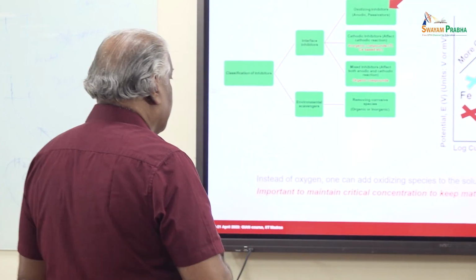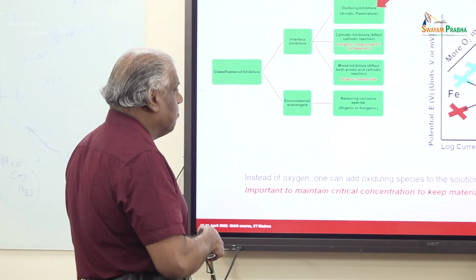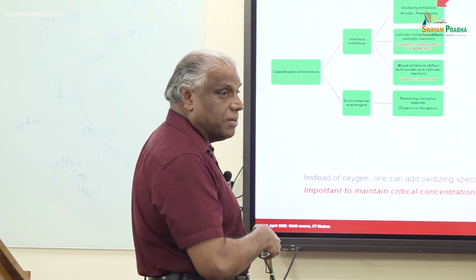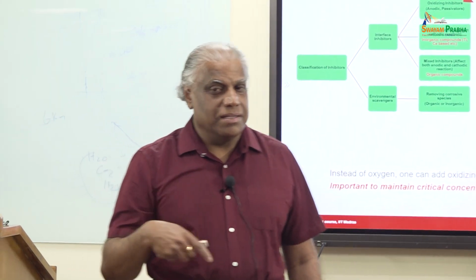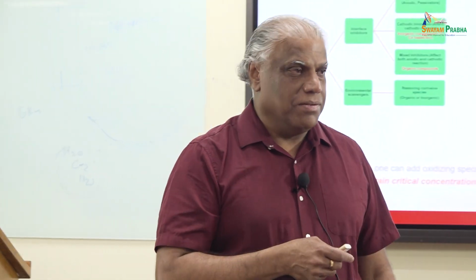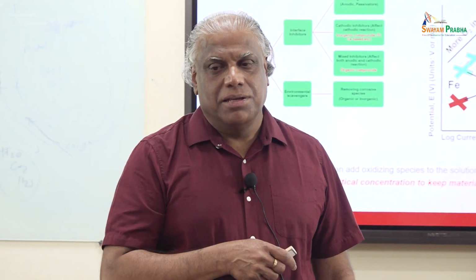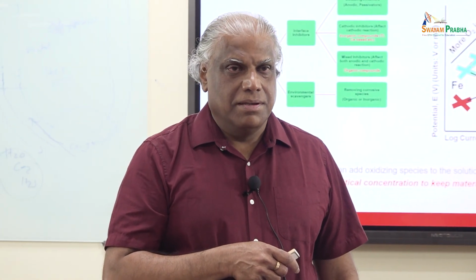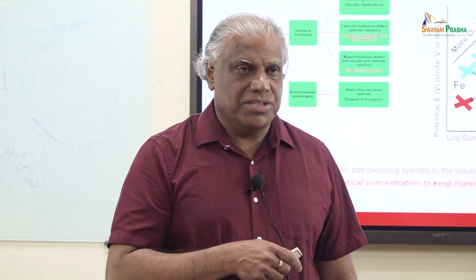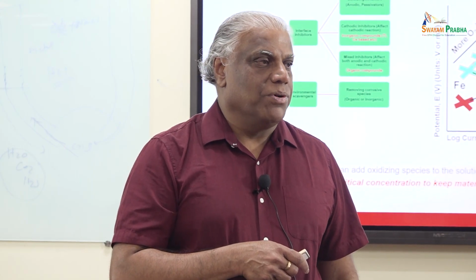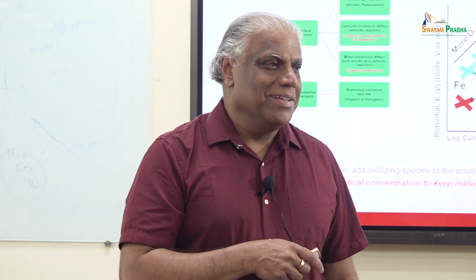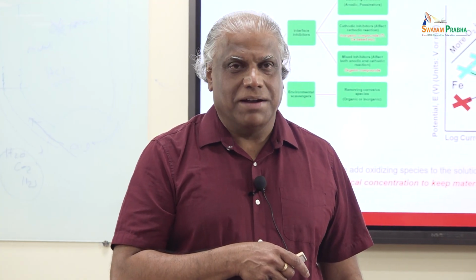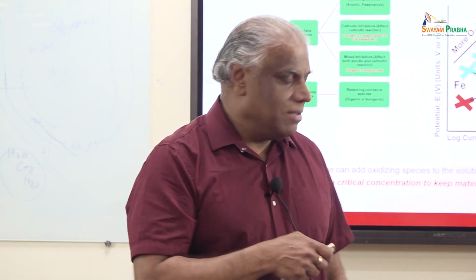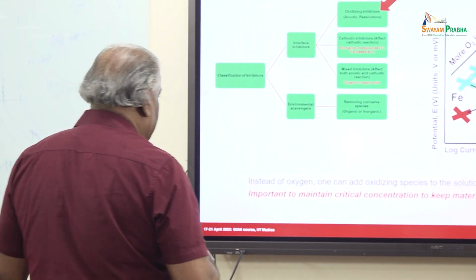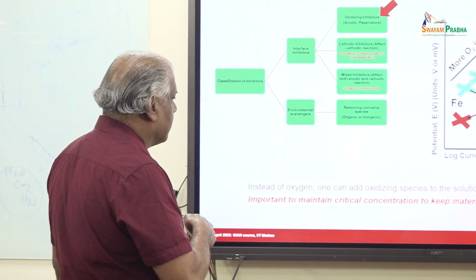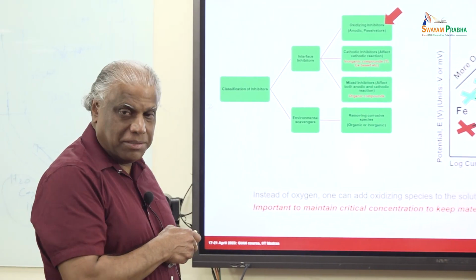So in effect, both chromate and manganate are being replaced today, and people are trying many other organic systems which can inhibit corrosion. That's what people are trying rather than using any of these oxidizing inhibitors. But chromate was one of the best oxidizing inhibitors from that point of view. You will see that chromate is everywhere, and it is hard to replace chromium, but we have to replace it because chromium is carcinogenic. But in this case, basically the idea is that you raise the potential by adding these chemistries, and then you put the metal into the passive region.